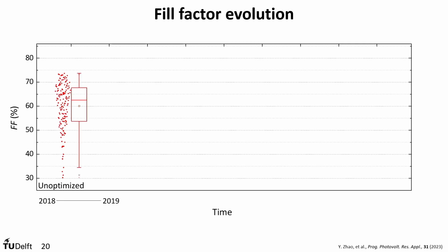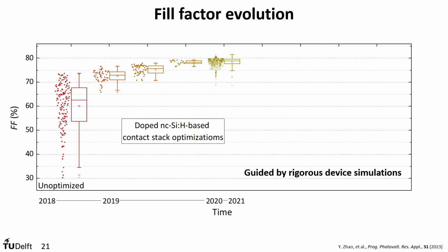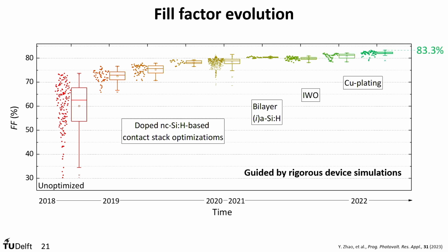We started with a very much scattered material that could give erratic efficiency numbers, and also it was relatively difficult to reproduce. Then with rigorous device simulations, we started to put in check all our doped layers with the nanocrystalline silicon-based doped stack. Then we also developed further the bilayer for amorphous silicon deposition for the passivation, then different TCOs, and then copper plating, up to 83.3%. This is, for us, a learning curve, and what also typically has to be done with all new PV architectures in order to get to extremely high efficiency.